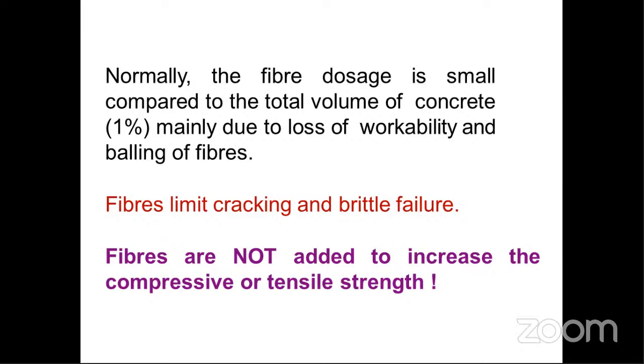Some people will add some fibers and produce some results, saying that strength has been improved, compressive strength has been improved, like that. But totally it is wrong. Fibers are not added to improve the compressive strength, right? It is not for tensile strength either. It is used only for improving the toughening mechanism. It is used only for improving the energy absorption capacity under various loading.